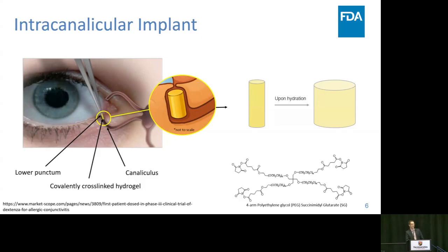This is accomplished by using a covalently cross-linked hydrogel in the case of the commercial product. And it uses this 4-arm polyethylene glycol that has terminal end groups that can react with amines and cause an amidation reaction for the cross-linking. So you can see that the insert is initially a smaller radius. It's placed into the punctum and into the canaliculus. It swells with a known swelling kinetics, and then it expands its diameter so that it basically matches near the diameter of the canaliculus.